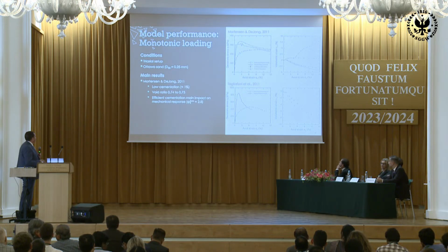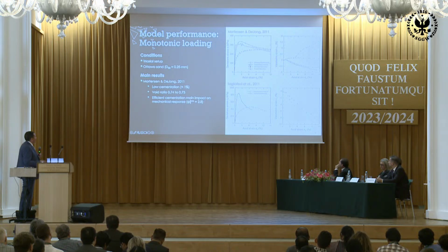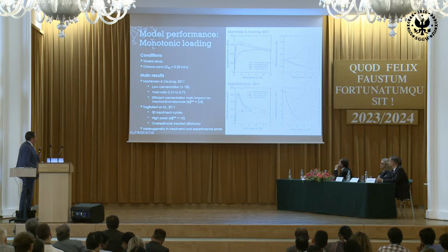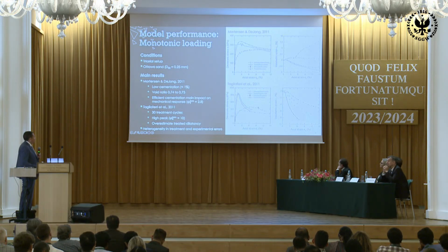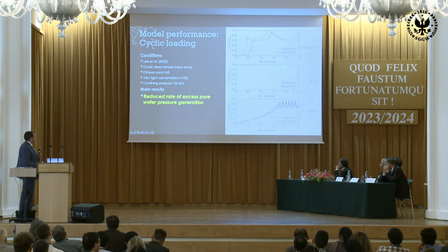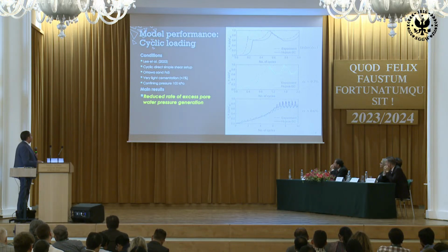Here are experimental results from the literature that we are simulating in different cases, but in all cases you see the treated and untreated case. The model is able to reproduce and to move from, let's say, a normally consolidated type of behavior to an over-consolidated behavior with a critical state that is not that much affected at the end, and also in terms of the dilatancy observed. More interesting is the cyclic loading, because I was mentioning the liquefaction process.